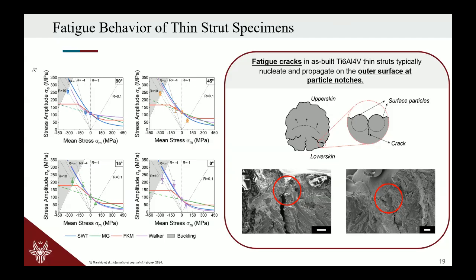We made the tests for fatigue on thin strut specimens, also changing the mean stress, as was already presented by Simone Mucchi in another session on Wednesday. And we have seen a very strong influence of the mean stress for the thin strut specimen, which suggests that this is a very strong and important effect that we have to consider for lattice structures.